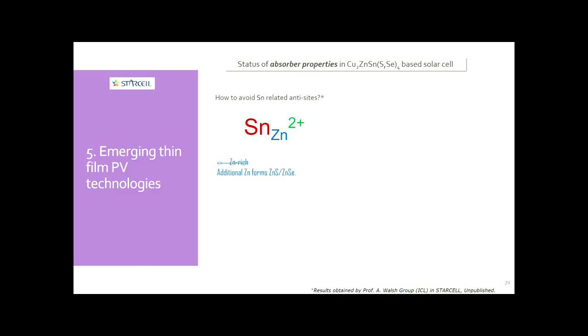And to do that, we have some technological solutions. Work in zinc-rich conditions in order to avoid this, but this forms zinc sulfide, zinc selenide secondary phases that are detrimental. Work in tin-poor conditions, but then we have copper-rich secondary phases that are conductive and kill our devices. Or finally, work with hole-poor material like an n-type material, but this material has a lot of acceptors. It's extremely complex to dope kesterite n-type. So these are not technological solutions, and we are now working on two possible strategies.